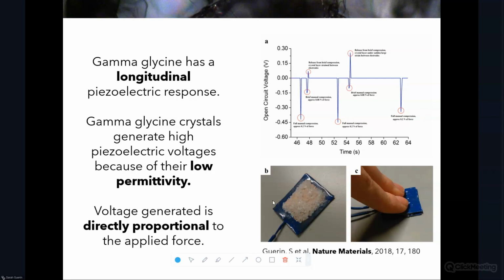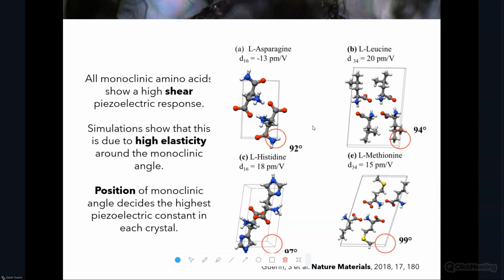So this was our very first amino acid energy harvester that we made here in UL. Just sandwiching our grown crystals in a very ad hoc manner onto our electrodes, tapping them, and then seeing what electricity came out of that. So that was hitting about 0.85 peak-to-peak voltage from gamma glycine back in 2018. But that wasn't enough to discover, I suppose, these materials and then validate their response. The benefit of using density functional theory to calculate properties is that we can then look towards understanding those properties.